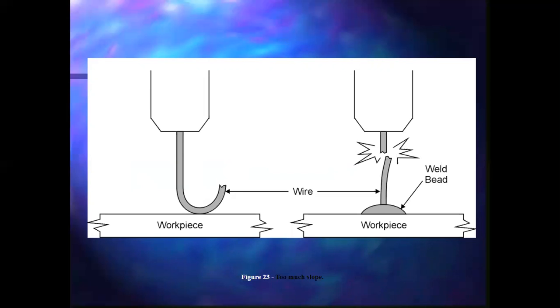On the other side of that, if your wire speed's too low and you've got a very high amperage, what's going to happen is that wire is going to come down, make contact here, and the amperage is going to blow this wire up. It's going to basically explode off the end of the gun. And that's not good because it can burn right back to the contact tip and jam that up. When I say explode, it's not an actual explosion, but it's a pop, and it blows that wire apart because we've got way too much juice and not near enough wire. So the way to fix that is to turn the amperage down or the voltage down, or turn your wire speed up. There are two ways of fixing those problems. I'll show you that when we get into class.